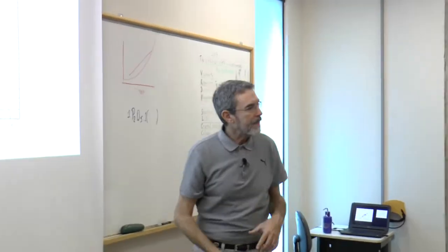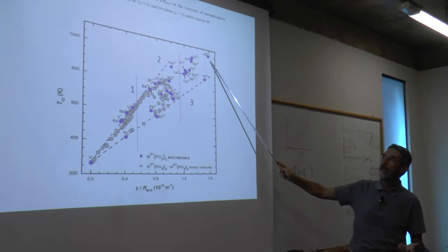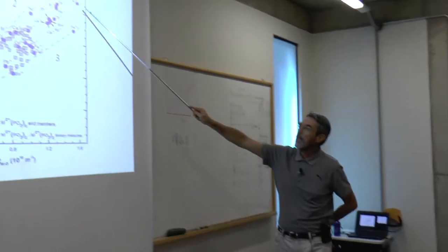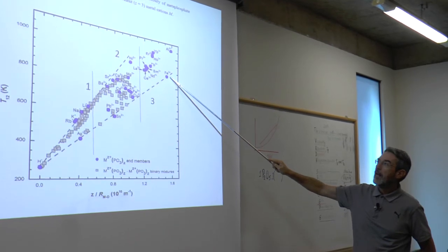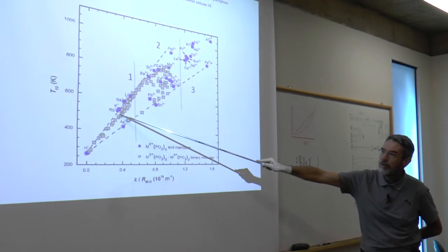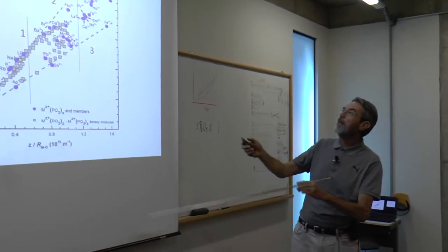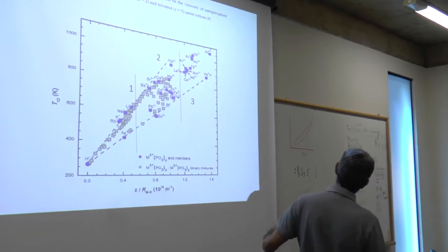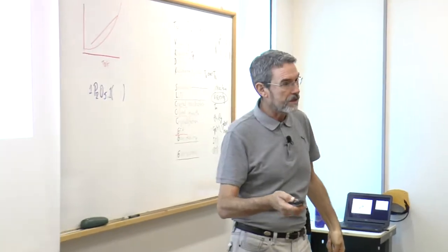So if you want a metaphosphate glass with high viscosity, add alumina. If for some instance you want to increase the viscosity, add alumina or iron 3, Fe2O3. If you want one with a very low viscosity, rubidium. Okay? And this can be done for other glass formers. This is a particular example for this kind of binary composition here, but similar plots exist for other systems.